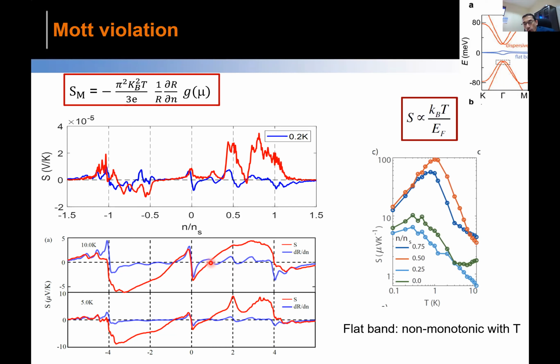Not only that, if I look at the thermopower magnitude as a function of temperature, here I have measured from 0.1 Kelvin to 10 Kelvin. You can see it increases monotonically at the beginning, there is a peak, and then it decreases. This you cannot explain by the Mott formula, because the Mott formula goes linear in temperature. So that again establishes that the approximate limit, the Mott formula we know for conventional metals and semiconductors, is not valid here.